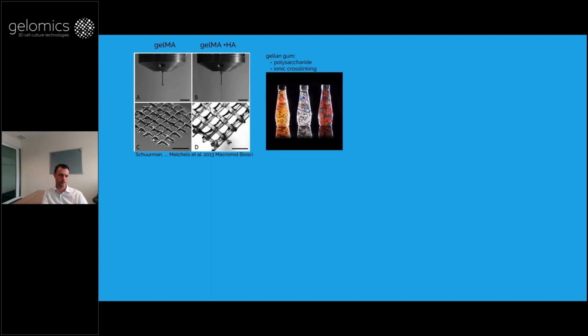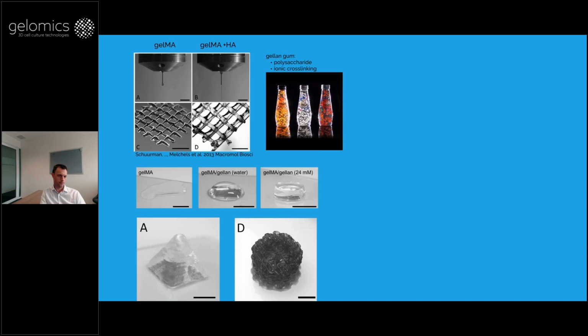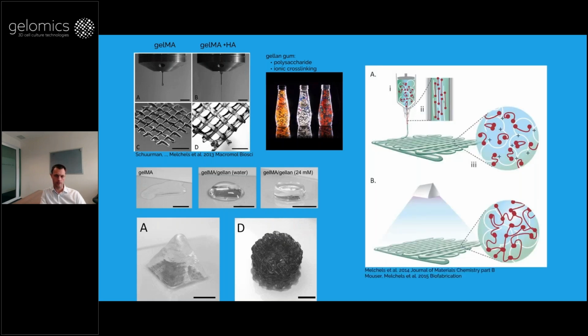Later we looked into gellan gum, a polysaccharide that can cross-link ionically, making a weak ionic bond that can be overcome by pushing it through a needle. So by tweaking the GelMA and gellan concentrations with salt, I was able to get the right rheology to print these. The top ones are molded, but you can see these are not photocured yet. Also, the bottom constructs aren't a solid pyramid, they have a porous structure. So the rheology here is optimized so you can build a structure, and even before photocuring, it already keeps its shape.